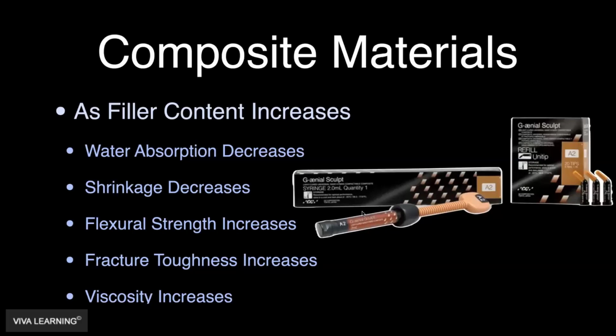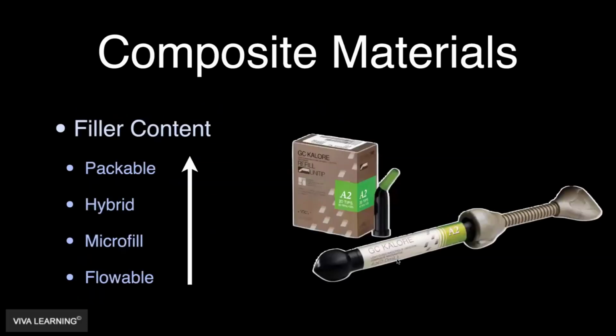So basically, generally, up until a couple of years ago, I would have told you that you could use a very, very basic rule of thumb. And that basic rule of thumb was that the more liquidy the composite, the lower the filler percentage. And the denser or firmer the composite, the higher the filler percentage. So literally, you could put composites out on a mixing pad in your office, and you could have made some very general rule of thumb decisions about the physical properties of those materials, and therefore what they were appropriate for clinically versus not being appropriate for from a clinical perspective.